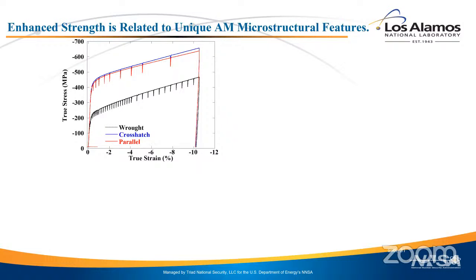The blue and red represent material that was made through parallel deposition, meaning your laser is always going like this, and crosshatch, where your laser on one layer goes 0 degrees and on the other layer goes 90. The crosshatch is maybe not obviously, but a much better way to make the material. But anyways, the strength parameters come out about the same. Both the powder bed additively manufactured materials are like a factor of 2 times stronger than typical wrought stainless steel. So going back to how I started this, we're going to try to probe the microstructure to see why the properties are so different based on the process.